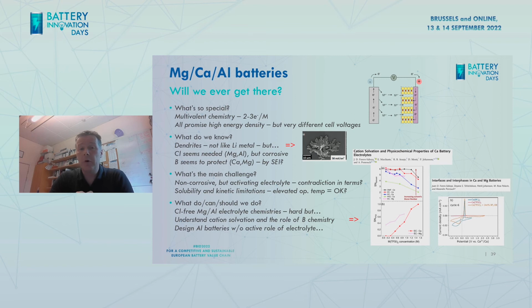We also see that for both magnesium and aluminium, there seems to be a need always for having chloride present. The problem with that is that it's also corrosive to a lot of other cell parts, and that itself turns everything that you do into a problem. Ourselves, we've been using tungsten current collectors just to have proof of concept, for instance, but of course that is not going to make it commercial. Another element seems able to protect by creating some kind of SEI.